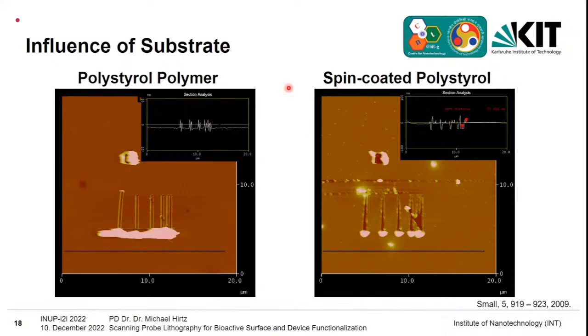And if you look at it, you can see also that the scratching depth seems, in the first run here, to be a little bit higher, though it's polystyrene as the sample material in both. But here it's easier to measure because the steps are wider. You can already see the substrate here also. This is a silicon oxide that is much harder than the polymer on top, so it's like a straight edge below. What you can do here on the polystyrene polymer brush is that afterwards you can also use sonication to wash away the debris, so what was scratched out.